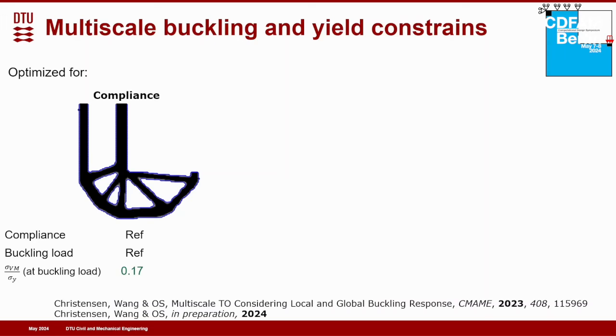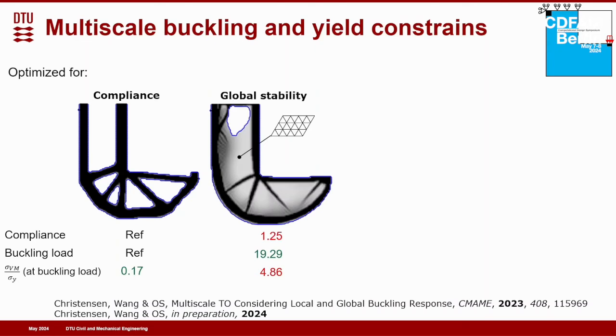Then we say, okay, let's optimize this structure for buckling. And nicely, now we get a lot of gray area, meaning that there's a triangular lattice structure there. And we see that the compliance goes up by 25%. So stiffness decreases, but we gain a factor of 20 in global buckling. So that is extremely nice, right? But, and that's sort of a side thing, the microstructure will yield. But let's wait a second with that.